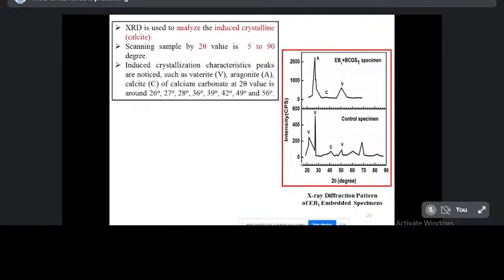Then we move to XRD. XRD is used to analyze the presence of calcium carbonate. The scanning sample 2 theta value is 5 to 90 degrees. Induced crystallization characteristic peaks are noticed, such as vaterite, aragonite, and calcite of calcium carbonate, at 2 theta values around 26, 27, 28, 36 degrees, 39, 42, 49, and 56.